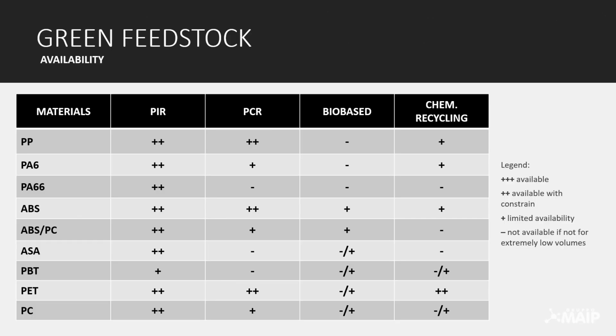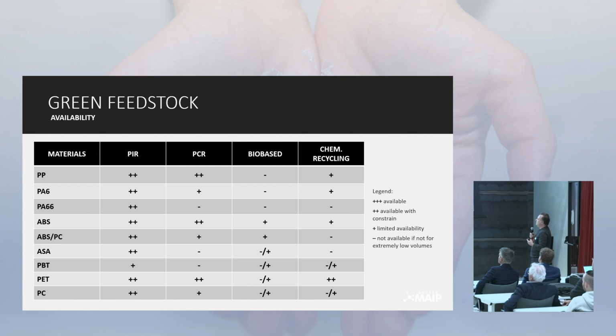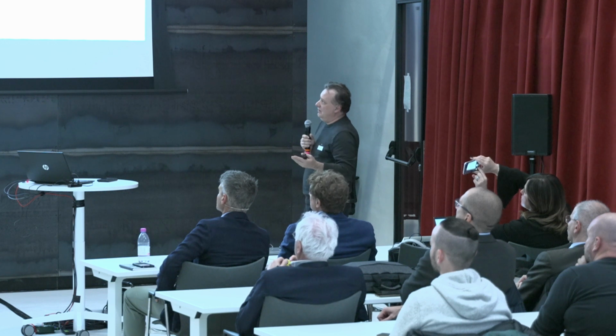Here you see, taking into account that we are talking about something which is changing day by day, but still, this is a picture of the situation today. What you can have post-industrial, post-consumption, bio-based, and from chemical recycling. PP, you can have even already a few amount bio-based, but it is not relevant. In the future it will grow. Polyamide 6, same story. You can have quite a good amount of post-industrial material, but you have almost nothing when it comes to post-consumption. Just a little polyamide 6 maybe coming from fishing nets, but there is not a real collection of post-consumption for polyamide 6.